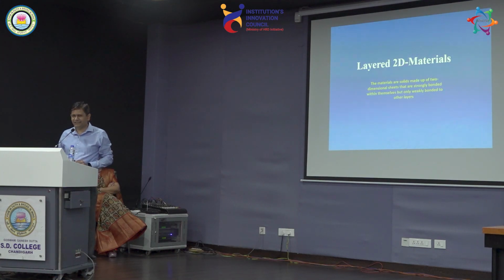So the problem actually, suppose you have a silicon bulk material, if you reduce one dimension, bring it to the nanometer, these are also 2D materials. But what is special about these layered materials? If you thin down silicon, then you always have dangling bonds. Dangling bonds means the bonds which are broken, unsaturated bonds, and then they saturate with the oxygen or water from the ambient. But in layered material, this is not the issue because there are no dangling bonds.